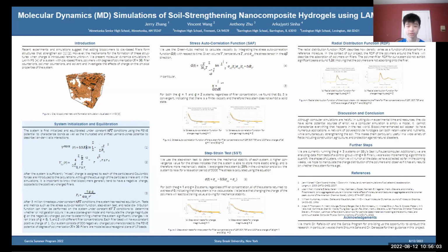The second test we performed was a step strain test in order to measure the mechanical stability of our systems. During the test, each system was elongated by 20% and allowed to return to equilibrium. We expect to see convergence to a non-zero value of stress if the systems exhibit gel-like behavior. For both charge magnitudes Q equals 1 and Q equals 2, we see a decay of stress to a value of 0, supporting the conclusion that our systems do not undergo gelation.